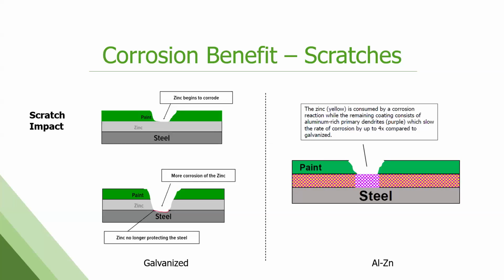On the aluminum zinc product, again, you have this mix of the zinc and aluminum. So even when the zinc, the yellow in this graphic, is gone, completely consumed, you have all this aluminum left that acts as a barrier coating. So you still have protection there. You still have something for the paint to adhere to, and the steel's not exposed. And again, it can be up to 4 times slower rate of corrosion than galvanized.